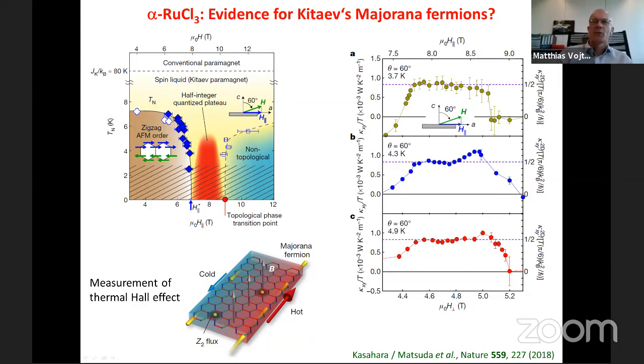And that is remarkable. Of course, quantization means it should be an integer. But here we talk about a system which hosts Majorana fermions, and the Majorana fermion, some of you may know, is formally half a fermion, and therefore a Majorana fermion edge channel is as good as half an edge channel. And so this here is a new type of Hall effect, of quantum Hall effect, if you wish. And this experiment, and one must say, we are still awaiting a more detailed experimental verification of this result by other groups. But if this experiment turns out to be correct with this interpretation, this is probably the most important experiment in the field for a decade, because it's the most direct evidence for Majorana fermions in this setting. Okay.